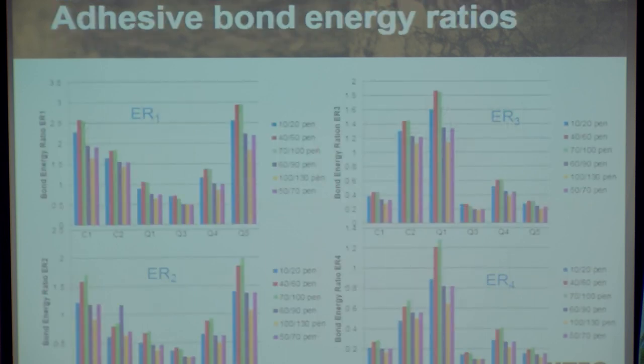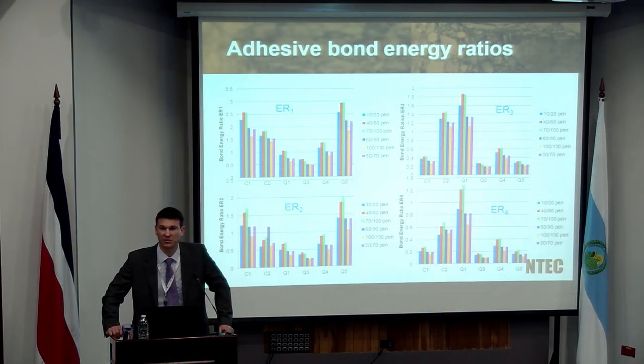And now we see massive differences. Whereas previously we saw graphs that showed only very subtle differences in terms of the individual parameters, now that we've got to a point where we are physically trying to represent the bonding between aggregate and bitumen in the dry and the wet condition in terms of one parameter, an energy parameter, we can now see that there are big differences between our individual aggregate particles and, to a lesser degree, but still some influence, in terms of different binders.